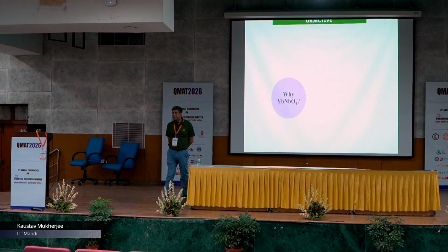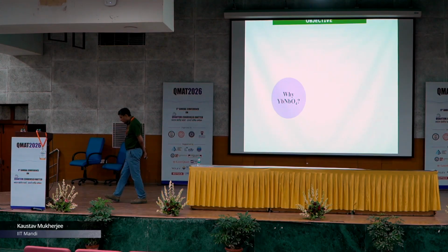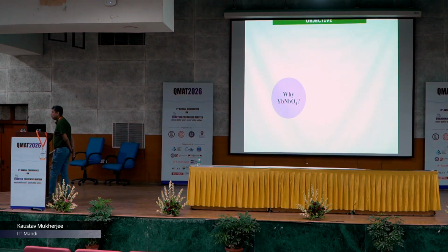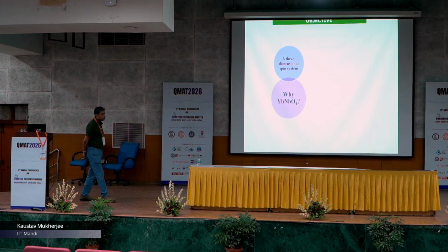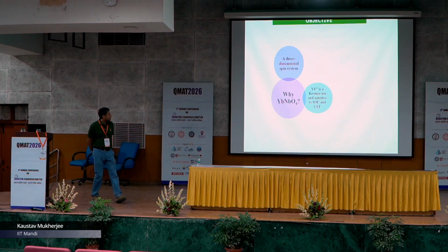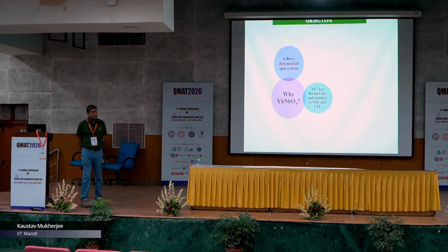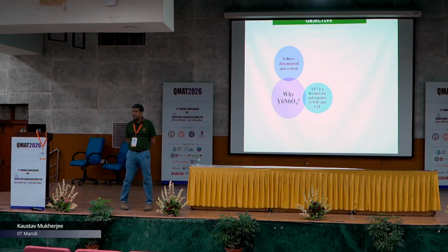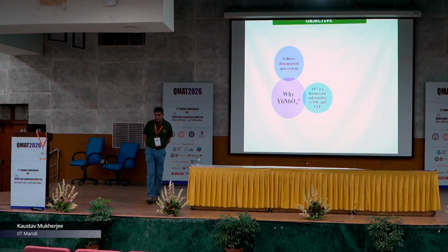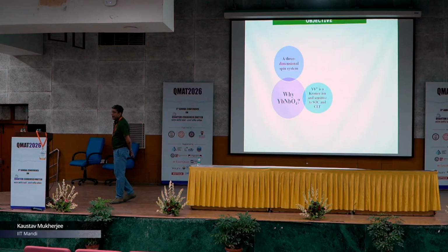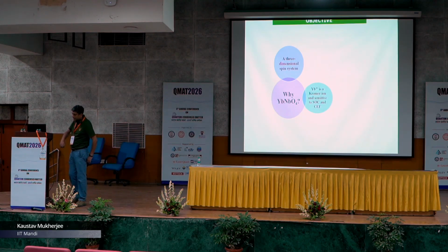Hence, coming to the objective of this study, we chose YbNbO4 for this work. Now, why YbNbO4? First of all, it is a three-dimensional spin system. Next, Yb is a Kramers ion, hence it is sensitive to both spin-orbit coupling and crystal electric field effects. Hence, we prepared this YbNbO4 compound using the standard solid state ceramic route and performed XRD. I have not shown the data here, and we did the Rietveld refinement, and it crystallizes in a monoclinic structure with space group I2/a.